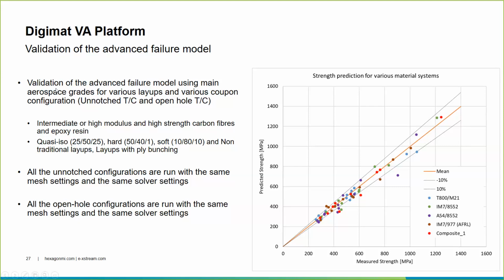So those materials have been tested on the unnotched tension compression and the open hole tension compression. They all consider intermediate or high modulus with a high strength carbon fiber and an epoxy resin. And those have also been tested on several types of layup. So we have here some quasi-isotropic layup, some hard layup with 50% of ply oriented at 0 degree, some softer layup with 80% of the ply oriented at ±45, but also some non-traditional layup and some layup that present some ply bunching.